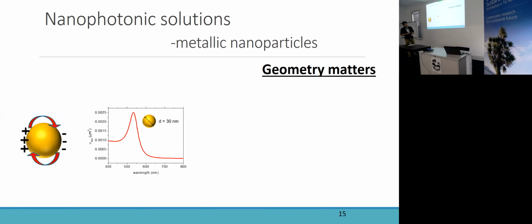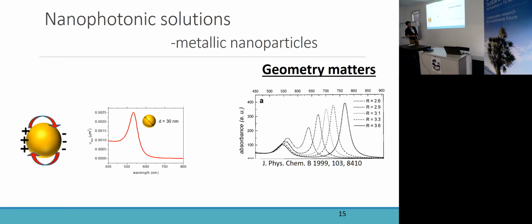And also, by changing the physical geometry of the nanoparticles, we can modify the optical properties. For example, here we expand the length of the nanosphere along one dimension, and then we have a nanorod. And we can see that the absorption spectrum redshifts with the growing length.